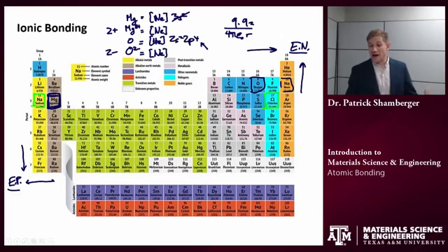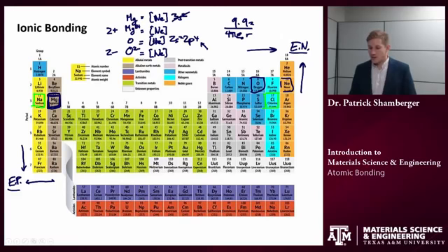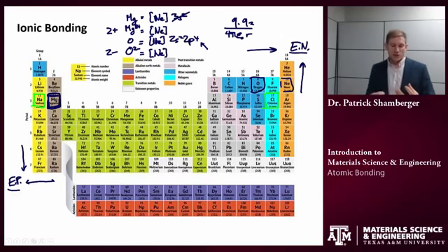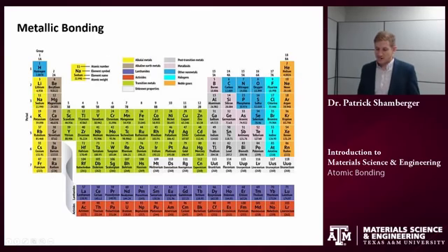So again, an ionic solid is a collection of ions. They have largely given up or accepted electrons to achieve more stable ground states. And then those particles are charged, and so there's some electrostatic interaction between the different charged particles. Ionic bonds tend to be very non-directional because, again, that Coulombic potential is a radial potential. It doesn't matter based on a particular orientation. So that's an example of an ionic solid.